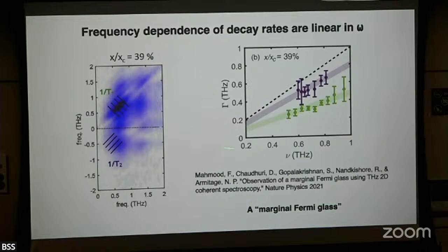And so if you could continue these lines down to low energies, the takeaway point is that there is no region at low energies where the system has some collective or low energy excitations which have line widths that are just smaller than their energies themselves. So the system is essentially always strongly interacting. And then another takeaway point from this is that the phosphorus doped silicon is not, if you will, mappable to something like an Anderson insulator.